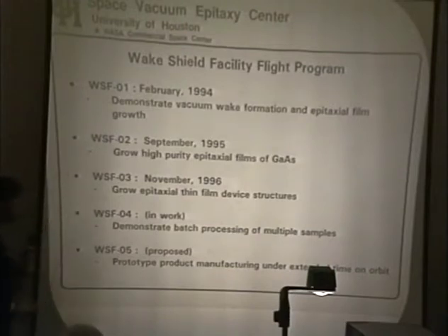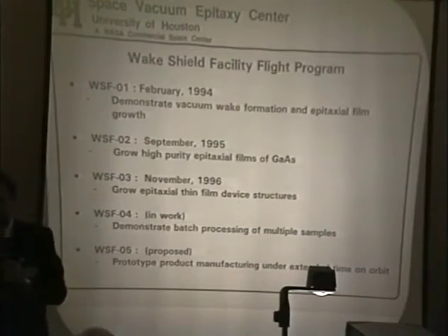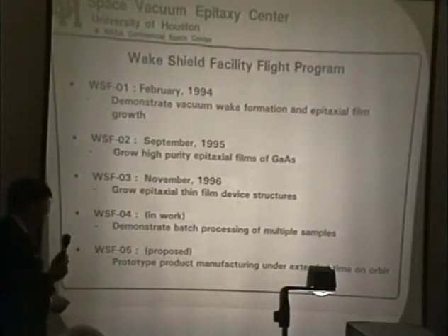Wake Shield 2 flew in September '95, on STS-69, and we grew the highest reported purity gallium arsenide films on that flight. Wake Shield 3 flew last November, and we grew epitaxial thin film devices. 4 is in work. We want to demonstrate batch processing. In other words, make more than 1, 2, 3, or 5 samples. Make 100 samples as an example. And then on 5, really do a prototype production manufacturing, something like 300 or 400 samples on orbit for an extended period of time.